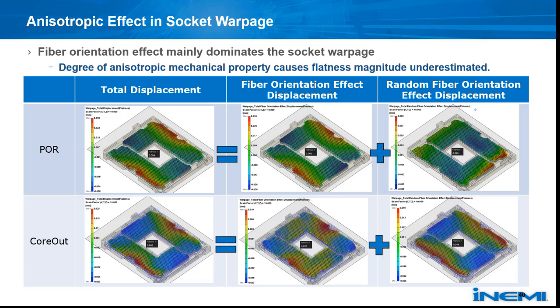So here we separate the total displacement into the fiber orientation effect, due to the fiber orientation, and the random fiber orientation effect, due to the temperature and the pressure, to help us distinguish which effect is the most dominant. In the result, the fiber orientation effect shows the same shape and even higher magnitude than the total displacement, while the random fiber orientation effect shows opposite warpage direction and small magnitude compared to the total. This indicates the anisotropy due to the fiber orientation dominates the socket warpage shape and magnitude. And the composite model underestimates the warpage magnitude may be due to us underestimating the anisotropic effect of the LCP.